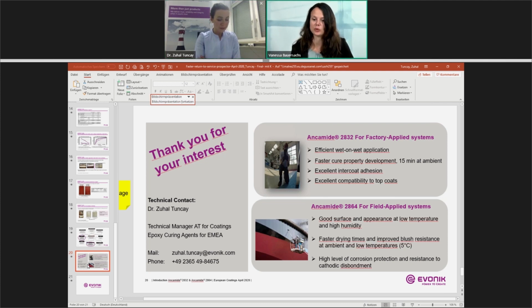Okay. Next question would be, is there any interaction between top coat and primer for recoatability? Such interactions may be between NCO and primer curing agents. Do I need to consider such interactions? Yeah, what we know is that we don't have any amine migration which reacts with the top coat. So in this case, I would say if we have an interaction, it's not in a bad way. Sure, for addition, there will be some interaction, but we don't see any surface defects.